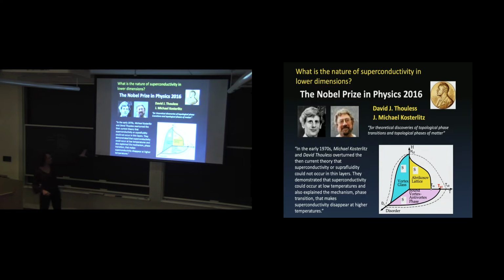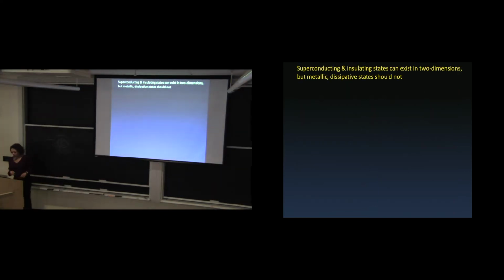So interestingly, even though this laid the groundwork for all future studies of topological behavior, it was really about how you could get superconductivity in a 2D system and what the mechanism was. So it's complicated. And they had a phase diagram here showing how, as a function of magnetic field, temperature and disorder, you have different sorts of vortex phases and phase transitions in superconductors. Okay, so one of the reasons that this Kosterlitz-Thouless type phase transition was especially interesting is because another thing about two-dimensional systems is that it's been predicted that